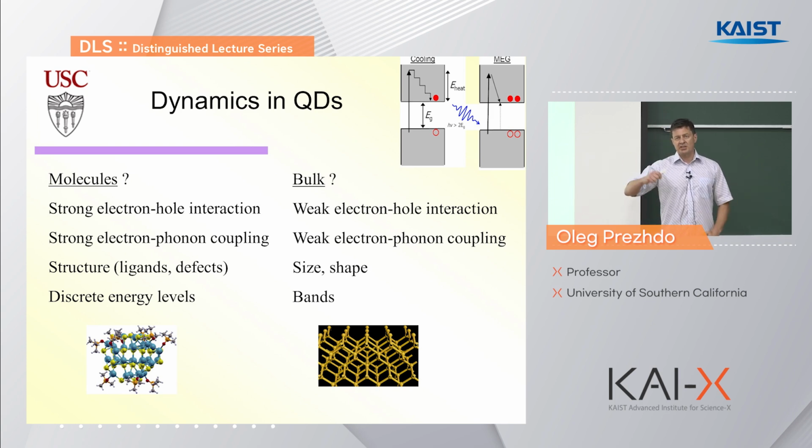Why? Because you have a solar spectrum that covers a whole range of energies. So if the energy gap of the material that you use, like silicon, is tuned to absorb in the red, because the solar spectrum covers mostly visible, a little bit of ultraviolet, some infrared, but mostly visible light. So you tune your material to absorb somewhere in the red, for example, and then you have much more energy in the blue and ultraviolet side of the spectrum, but all this extra energy is lost to heat. And that's why in a simple solar cell material, you cannot have efficiency more than 32%, a theoretical limit people developed.